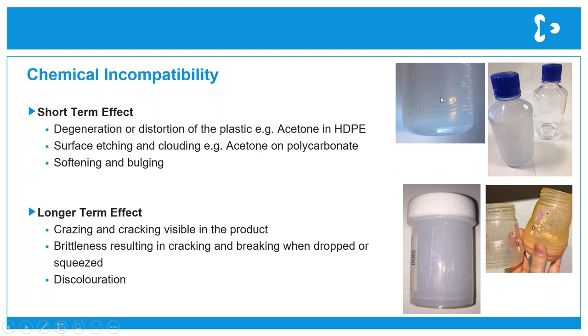And then we can see more long-term effects of using a chemical or a reagent with a product where the polymer isn't suitable for use. Here you can see a polystyrene container that's been used with an incompatible chemical, and over time it's caused cracking and crazing. On the right you also get some discoloration, and this can occur in similar circumstances. These are all aspects that you need to be mindful of when selecting the correct polymer for your specific applications.